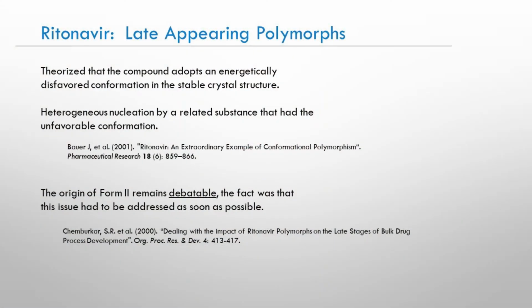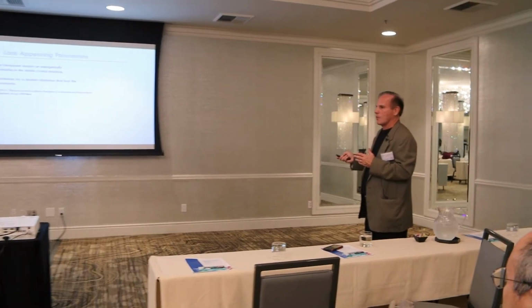They were off the market, I believe. This was first in class, I believe, of one of the protease inhibitors, and it was growing in sales very rapidly, and all of a sudden they had to withdraw from the market while they reformulated. They theorized that the compound adopted an energetically disfavorable conformation in the stable crystal structure, and that's why it didn't nucleate very well.